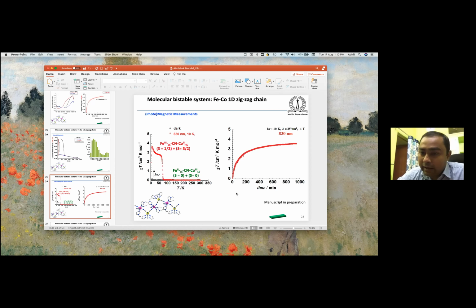But again, you have to compensate, because you do not get all the nice interactions that are possible at low temperature. We have tried using one single crystal that is a little big, to see if you can see a field effect when you use the high field. We observed that, but it is not a significant effect.